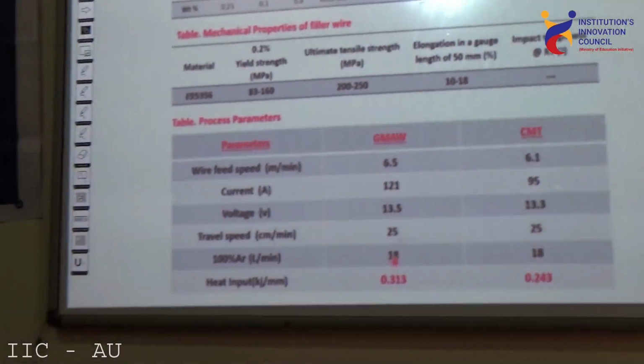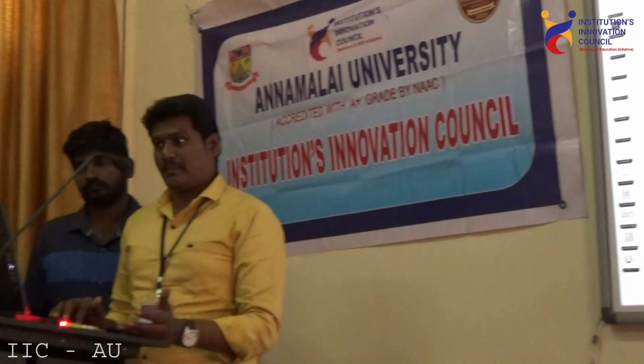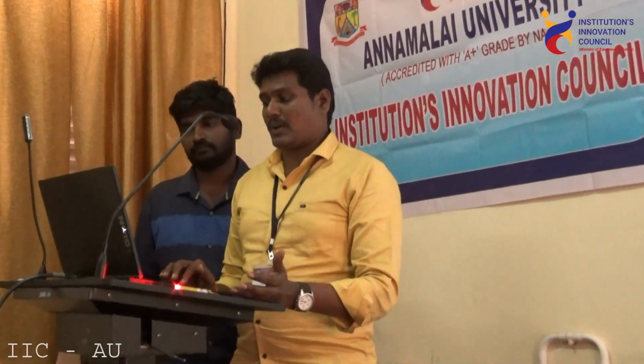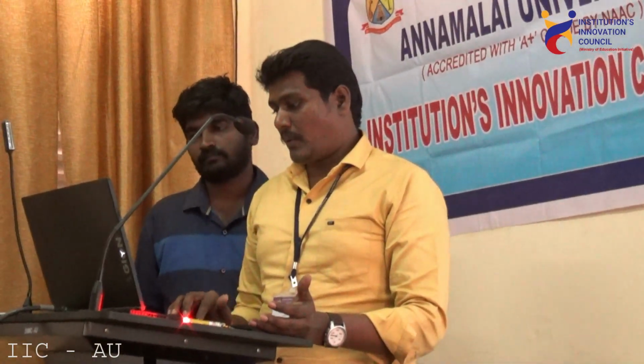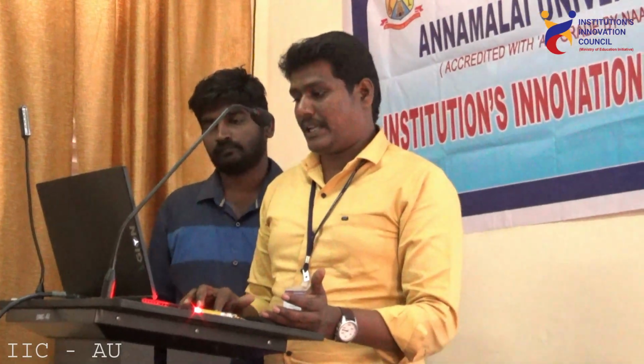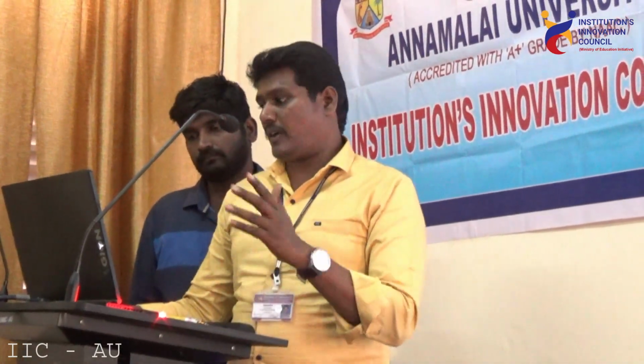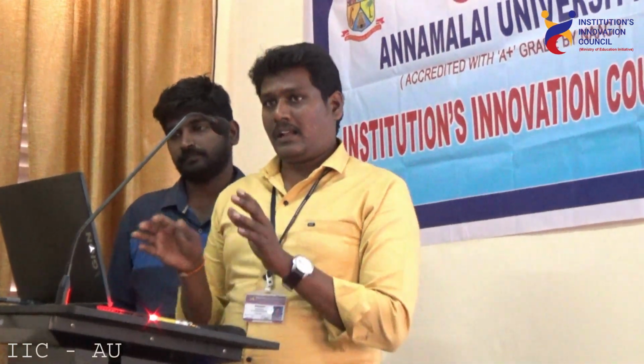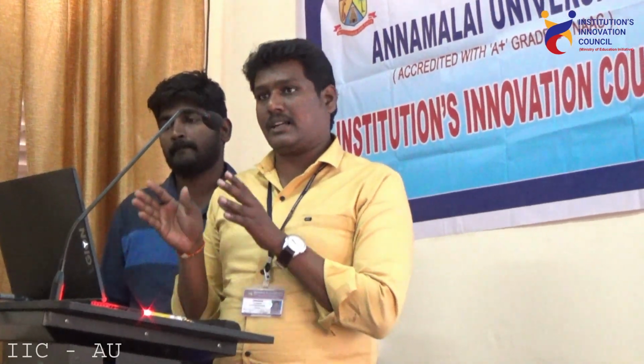One is for the GMAW process, this is the process parameter, and for the CMT process, this is the process parameter. The one thing that we have to look at here is the heat input, which is 0.313 for the GMAW process and 0.243 for the CMT process. In this, we could clearly see that the CMT process has low heat input.